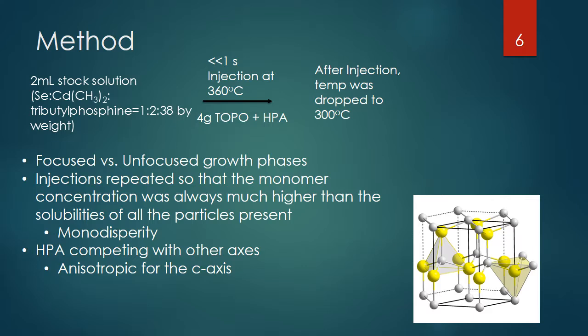TOPO and HPA are actually surfactants that mediate the growth of the cadmium and selenide atoms. This injection happened for less than a second because that is about all you need for the nucleation of these cadmium selenide nanoparticles to start.